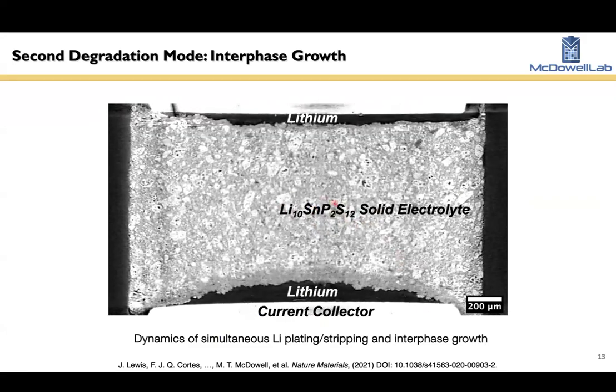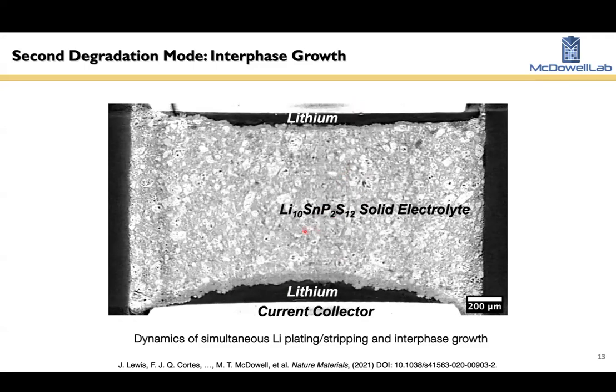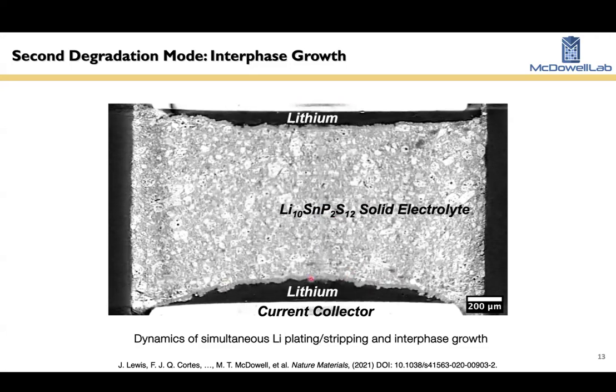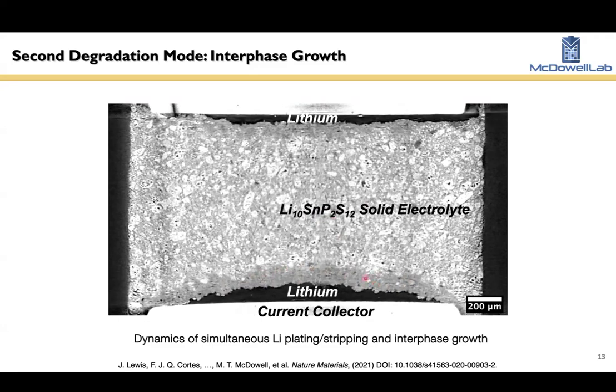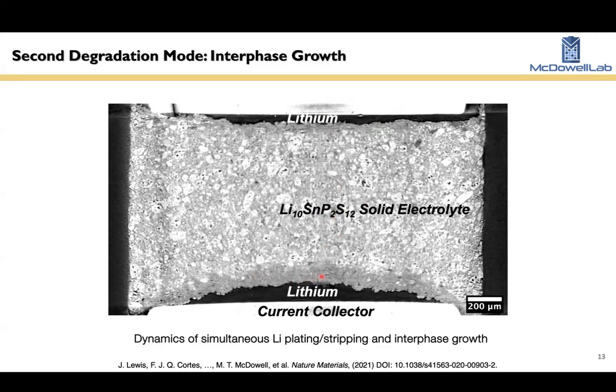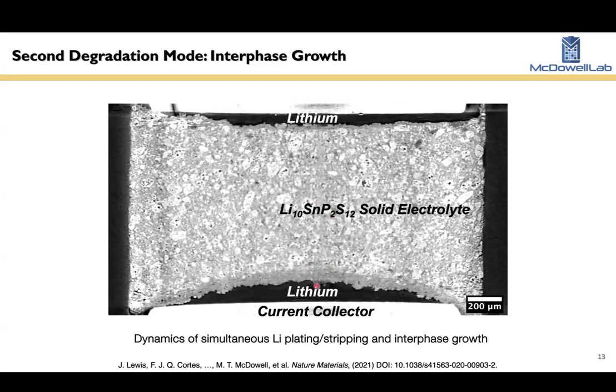This particular material, lithium tin phosphorus sulfide, is really quite unstable with lithium. You can see here in this video, this is an X-ray video now over about 10 hours of an experiment. And what you're seeing is this intermediate contrast phase that's forming at the bottom and the top interfaces where lithium's present. This phase is actually interphase. It's an interface layer that's growing into the solid electrolyte. So it's growing dynamically, and it's really quite thick. So this is not good for a real battery. You'd never want this to happen in a real battery.